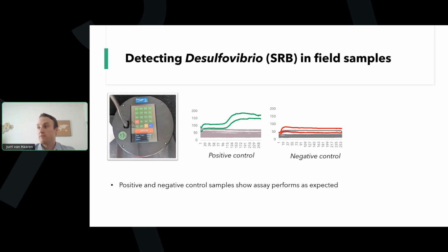We had samples that we knew had that species of microbe in there, and one sample that we knew did not have the species. With the positive control, you get these nice amplification curves, and the screen shows a positive result, suggesting it works exactly as expected. With the negative control, you don't see amplification curves, you see a negative result on the screen. So the control samples performed exactly as you would expect.